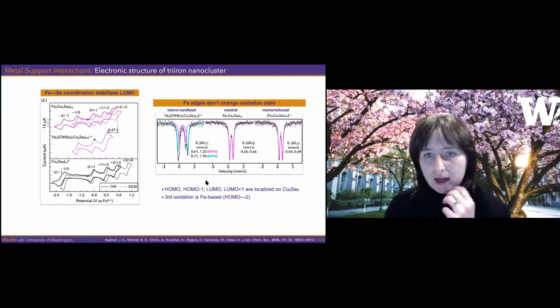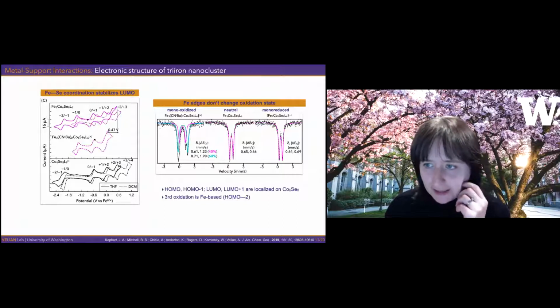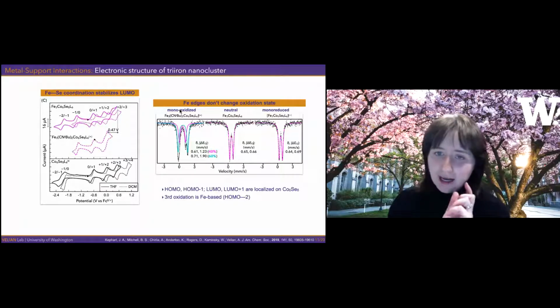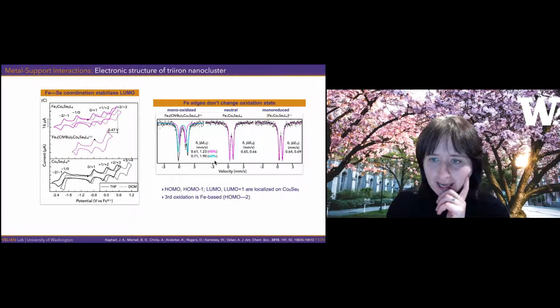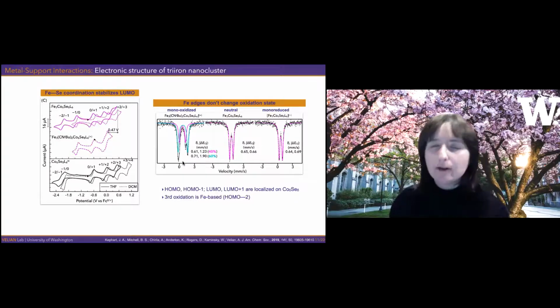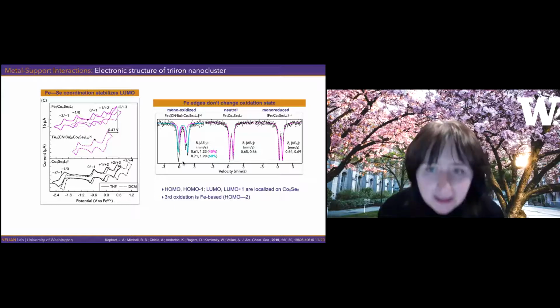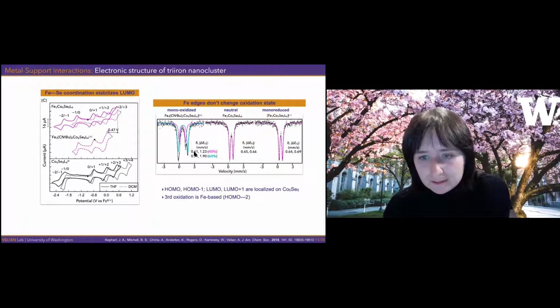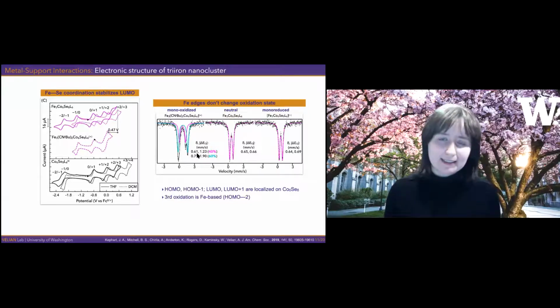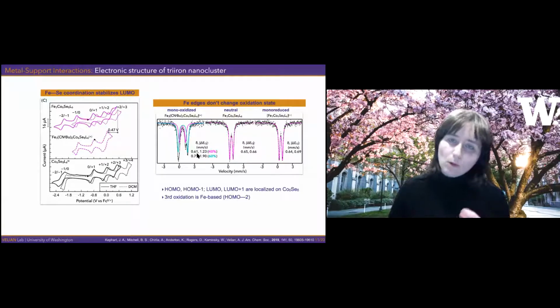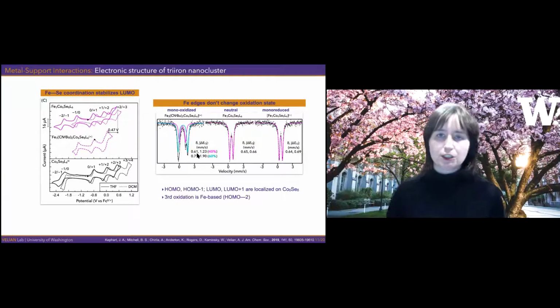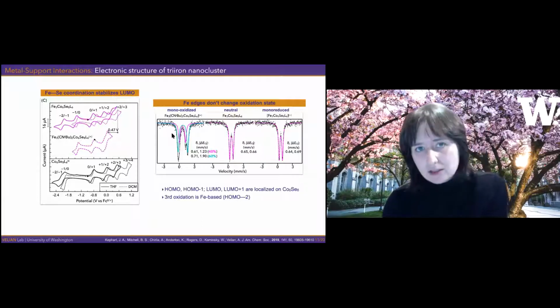And if we couple this with Mössbauer spectroscopy, which is shown on the right side, what you want to take a look at here are two things. One is the position of the isomer shift, and that's really the most indicative of the electronic structure of the iron. And if we look at these numbers, if we go from the mono-oxidized to the neutral state to the mono-reduced, this value doesn't change significantly. You're still really around 0.6, which is indicative or associated with an iron 2, not with an iron 3. So this sort of confirms what we thought, that the HOMO and the LUMO levels that you probe by oxidation and reduction are localized on the cobalt and not on the iron sites.